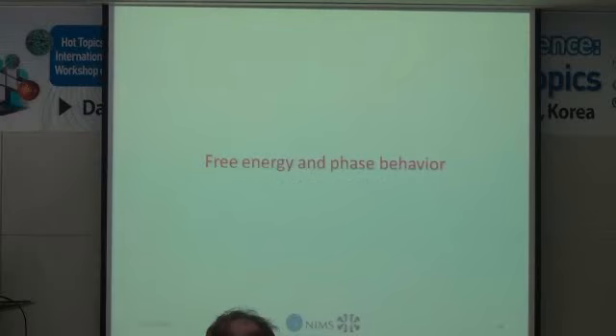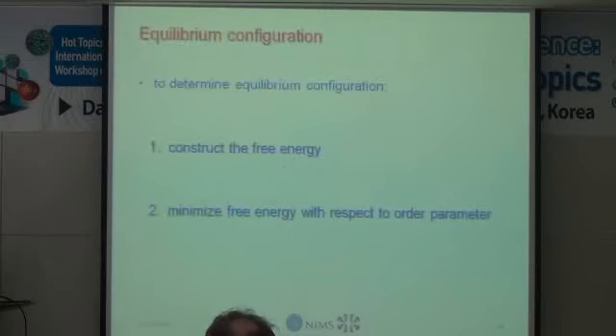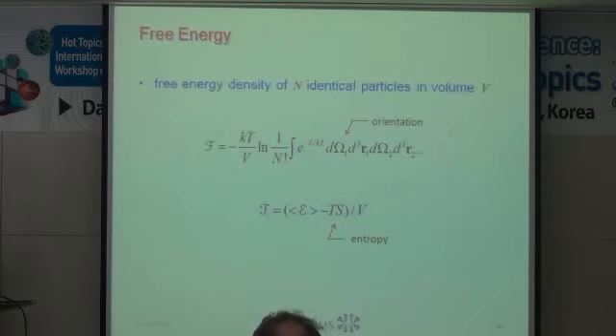Now, free energy and phase behavior. So to understand the equilibrium configuration of systems, one needs to minimize the free energy. So the free energy is basically the interaction energy plus the contributions from entropy, and it's this quantity that has to be a minimum in equilibrium. So one somehow has to construct the free energy and then minimize it with respect to the order parameter, and then we know more or less what happens.